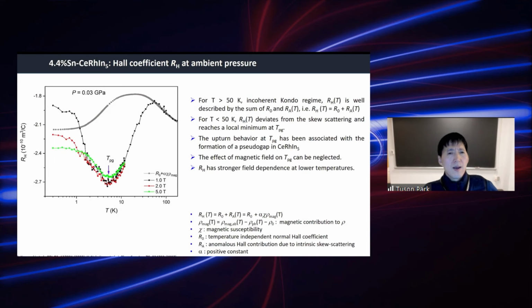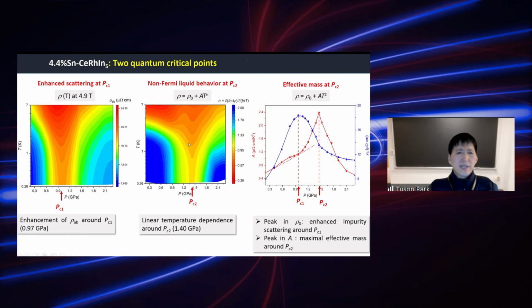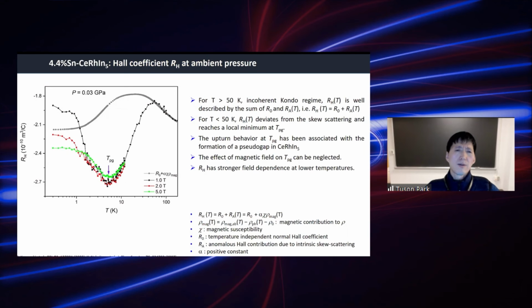Okay, so what is this critical point 1? We know PC2 is the AFM QCP. So in order to understand it, we did a Hall measurement for this compound. And this is data at ambient pressure. At high temperature, the temperature dependence can be well explained by two terms, namely the normal term and the skew scattering term. And when you estimate it, it explains pretty well.